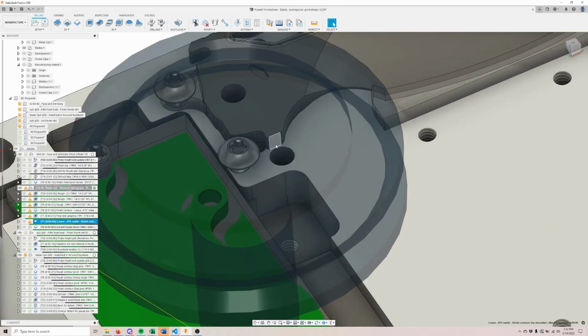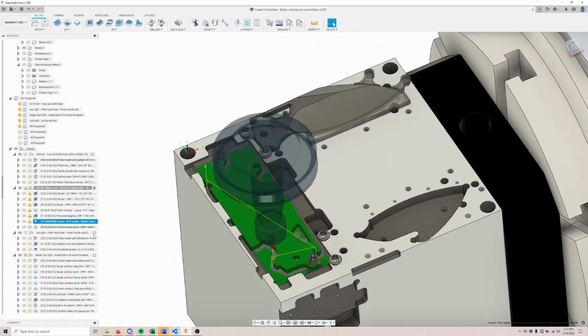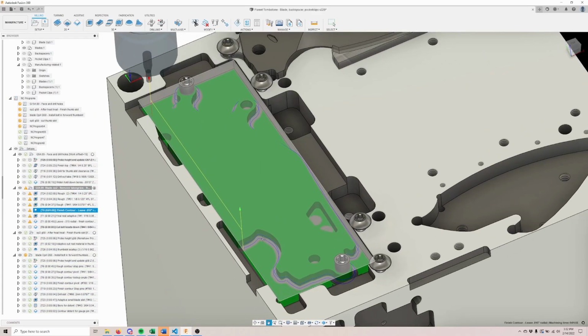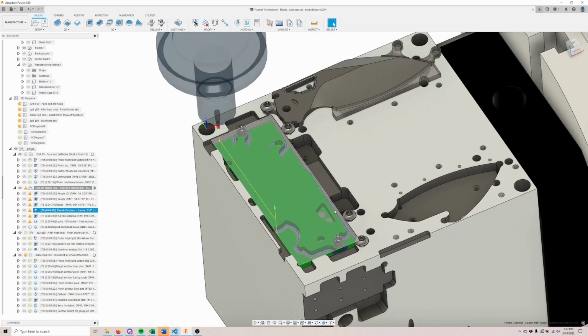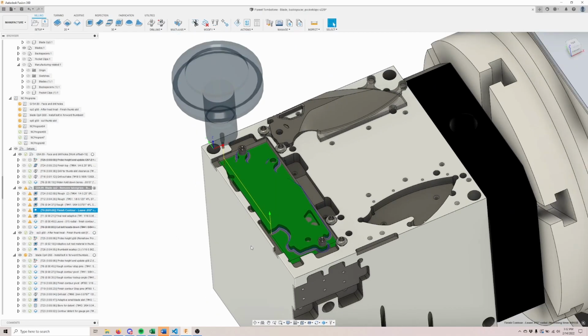The reason there's a gap right here is because I'm actually leaving 15 thousandths on the entire outside, and the reason you leave 15 thousandths is because it can grow or shrink during heat treat, and you need material to cut away. So I figured 15 thousandths was enough. Some people leave a lot more, like 100 thousandths. I thought that was a lot of material to have to hard mill. So I said I'll give 15 thousandths a shot, and it seems to be working really good.